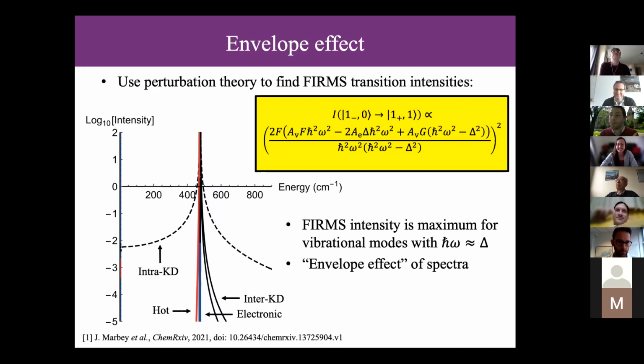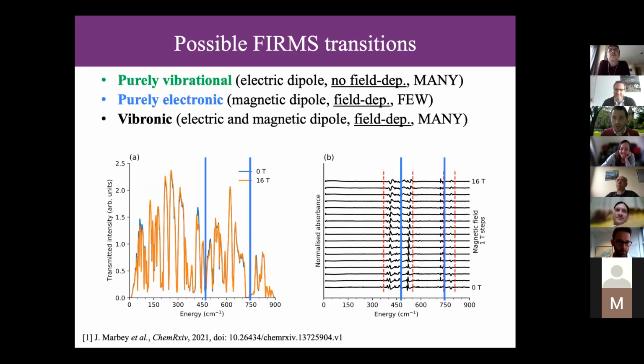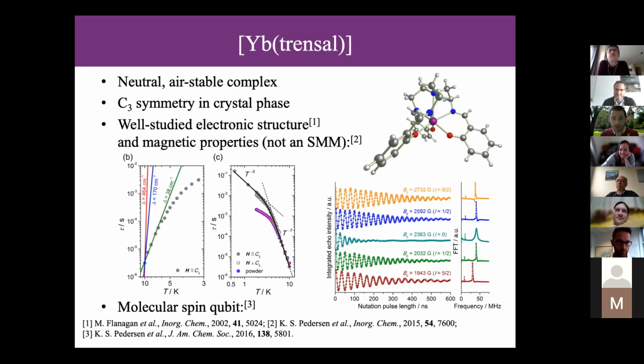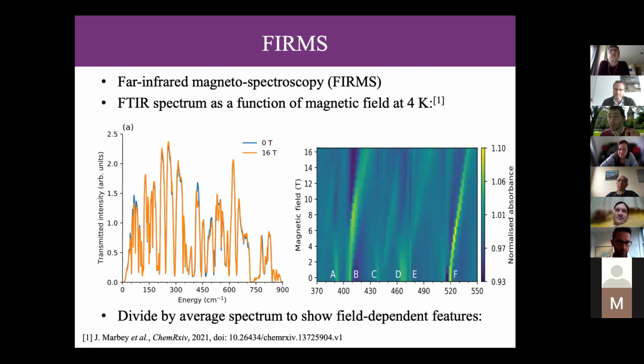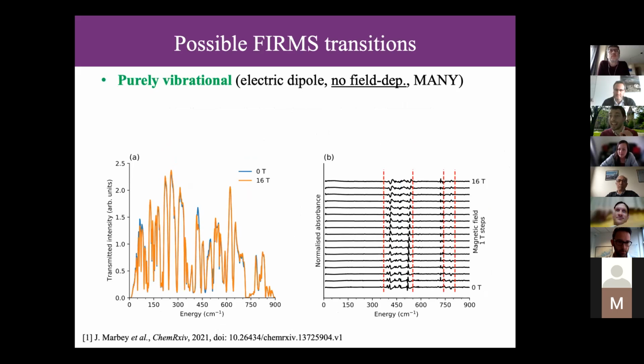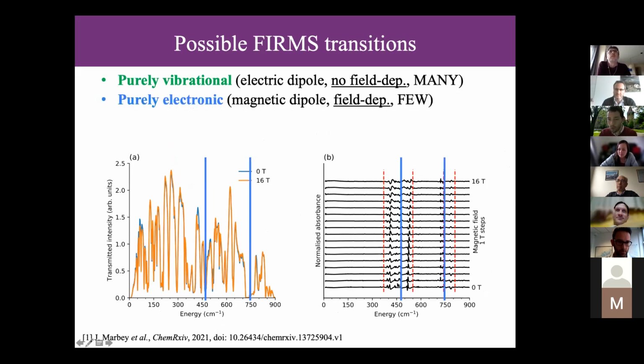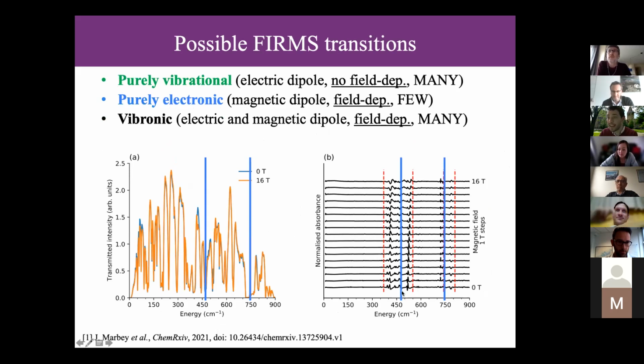I know. But remember, the problem is the magnetic relaxation dynamics of this molecule are all 2-phonon. So I would need to do this, fully crystal phase, everything, all of the acoustic modes, right? Which in terms of, if you're looking at the acoustic modes, remember, these are very, very low energy vibrations. And if you're doing intra-Kramers doublet transitions, you would see only the acoustic modes here near 0. Of course, if you're doing inter, yes, you would have all the acoustic vibronic transitions right next to these pure electronic excitation. But again, that's really hard. That's a really hard region to split out.